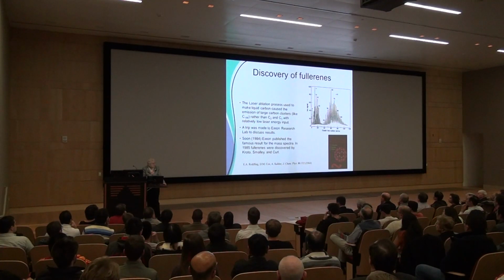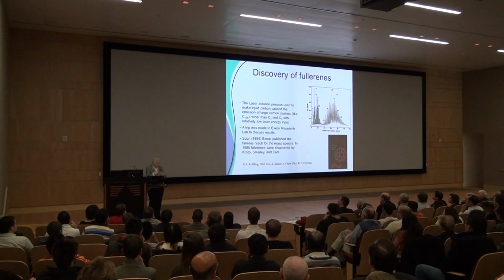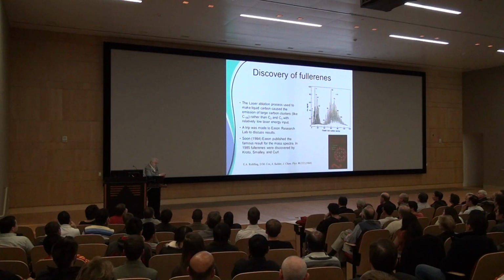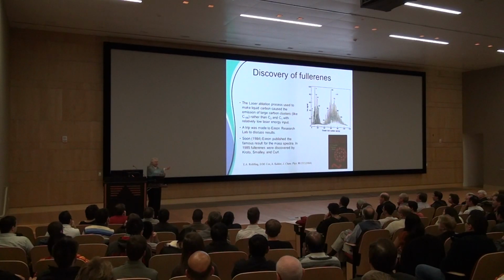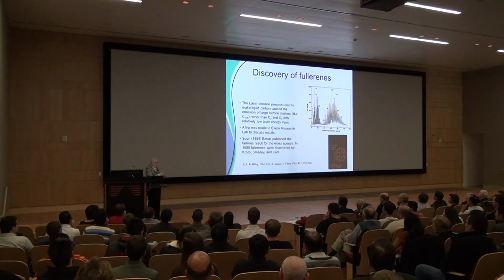When they got a little bit more energetic, it pulled out big chunks, and we could tell that because our clothes got all sooty. So we knew that something funny was happening, and it gave us the idea to measure. Here's a stick of carbon, and you have a laser coming into the front. I'm not going to point this at you, don't worry. And it comes out like that. But along with what comes out were big chunks of material, and we could measure how much material vaporized for how much energy went in. From that, we could figure out that we had something on the order of C100, very big chunks.